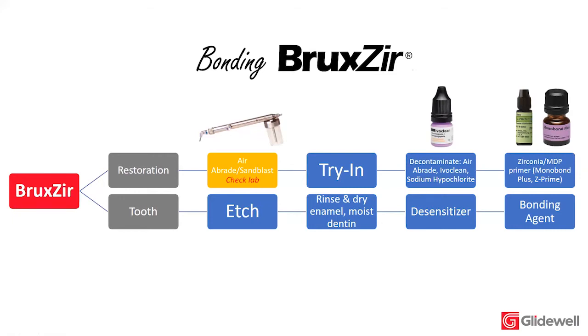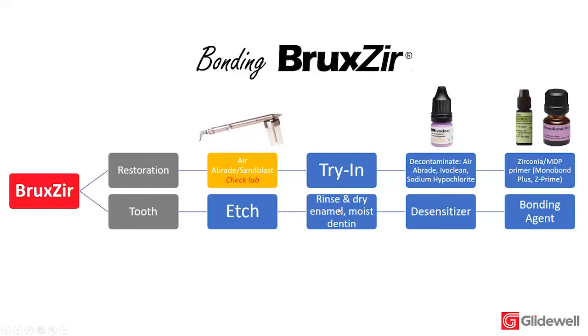On the tooth side, what you just saw, I typically will follow a total etch technique. After we etch, then I do rinse and dry. Of course, we do want to check the enamel for that frosted appearance. And sometimes through that process, we could desiccate the tooth. And if we dry the tooth out, whenever we're bonding, it's super important that we have a moist dentin surface, because if we over dry the dentin, the bond strengths will significantly decrease.